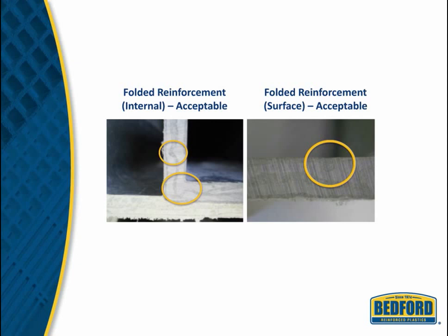Any fold that is over 50% through the product's thickness is rejected, regardless of whether a crack is present. Any crack that penetrates through the glass ply at a mat fold area, regardless of the depth of the fold, is not acceptable.